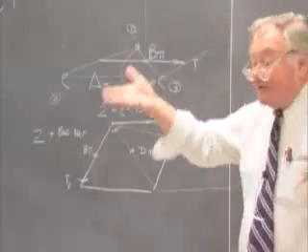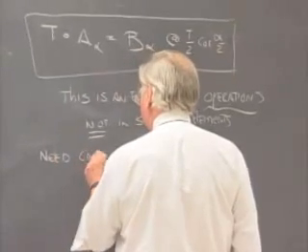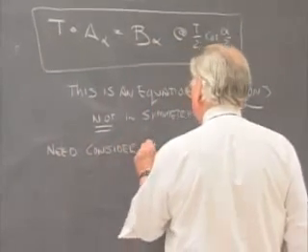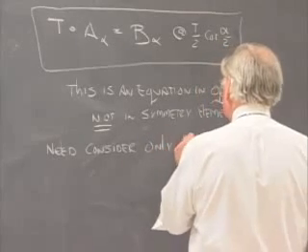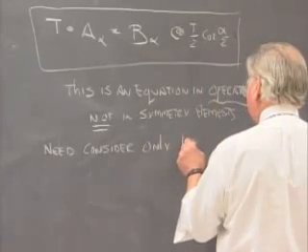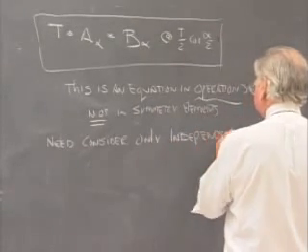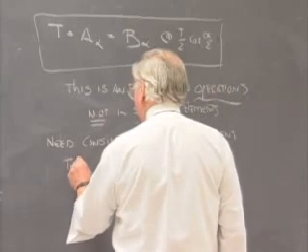And we don't have to ask what happens when we go 3 translations over. There's going to be another operation of 180-degree rotation in that translation, but we really only need bother about what goes on the edges and in the interior of one unit cell, because whatever is there has to be repeated by translation. So in making these additions, we need consider only independent translations, that is, not related to one another by the rotational symmetry. Independent translations that terminate within the unit cell.